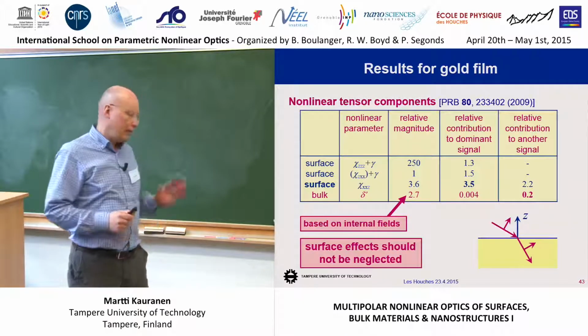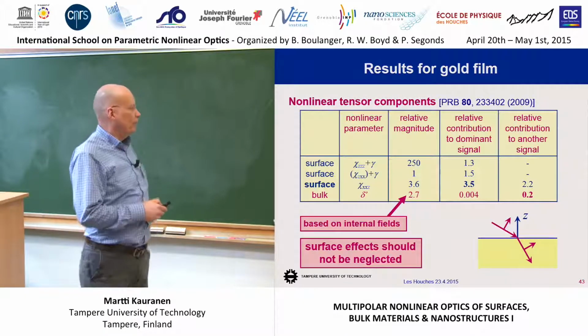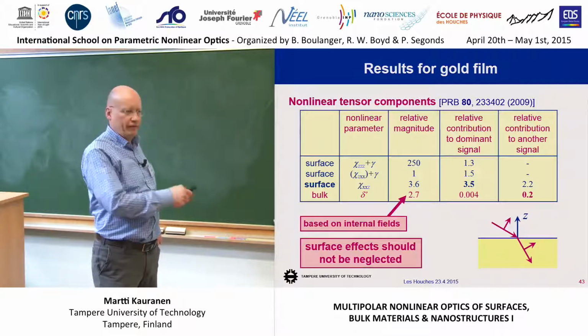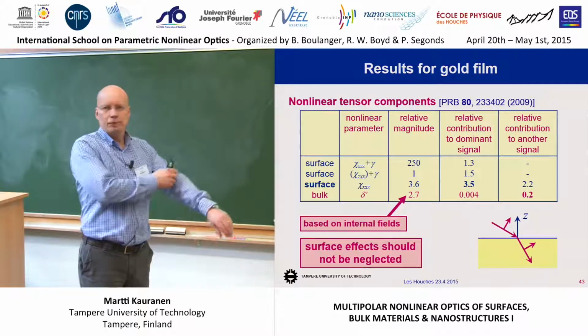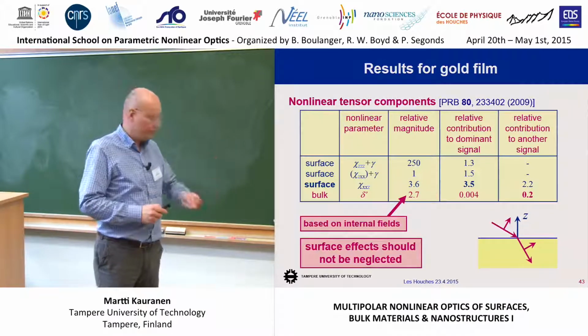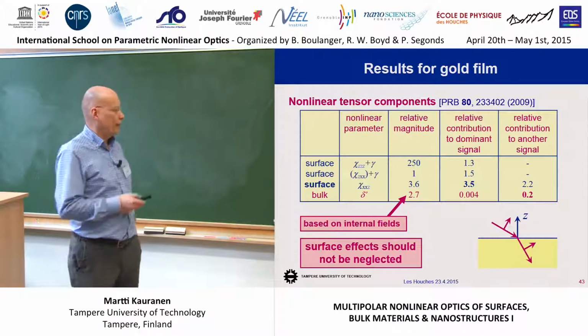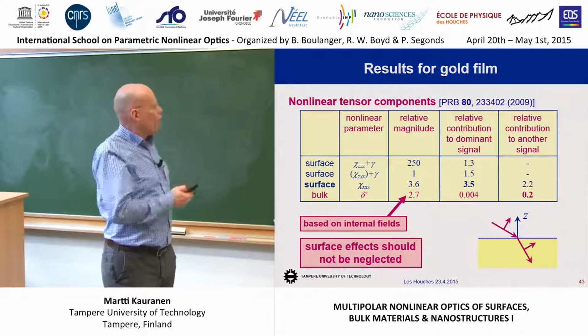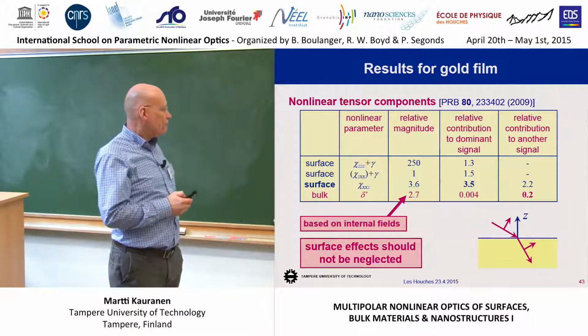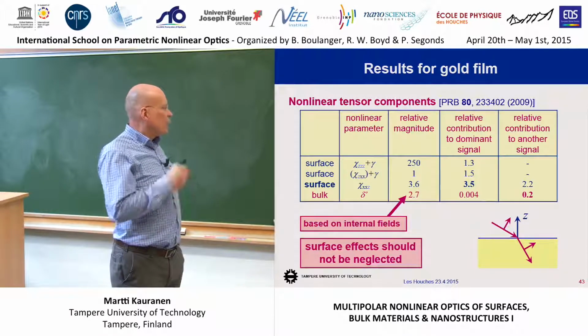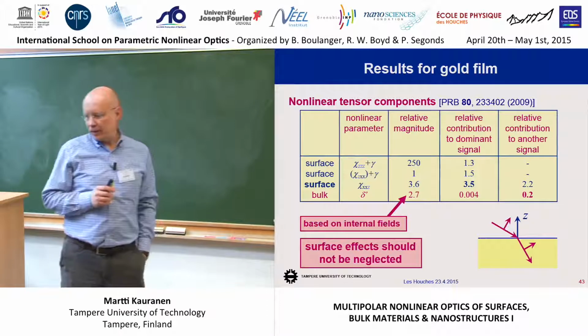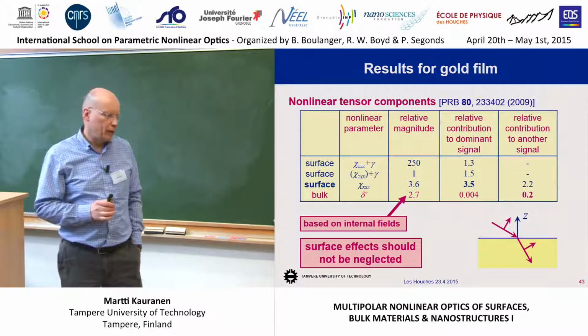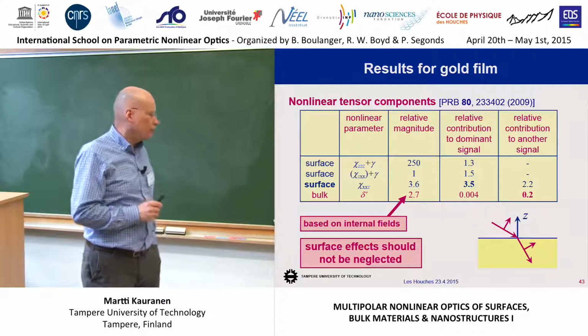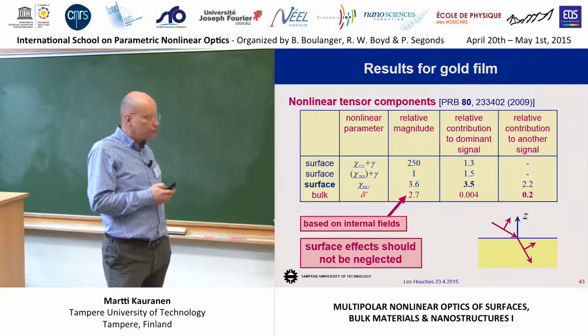And in the end, of course, you would like to build a model which takes into account all these effects. And it's doable. Some groups have tried to do it and so on. So there's no fundamental problem anymore. Okay, then, so we were really happy here that we were able to measure the surface and bulk contribution for the first time for a metal film.